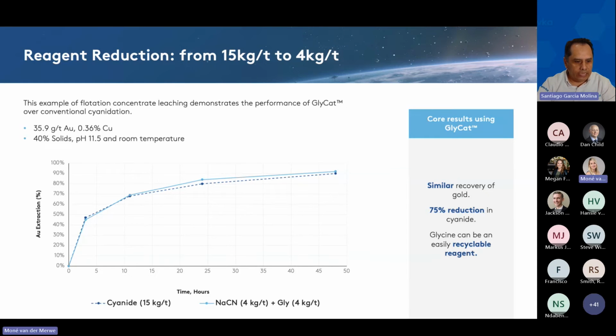Also, because the glycine used in the test was reported as glycine added during the bench scale tests, it doesn't include any recycling, which is achievable during operational conditions. Also, the gold recovery was slightly improved with the glycat conditions, which is another benefit observed in many cases when using our technology.